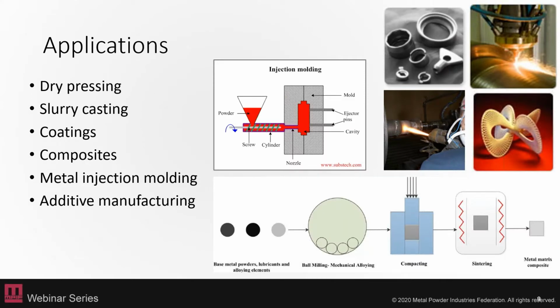And just on a high level, the powder metallurgy field is so broad and includes so many different areas that each of these areas are going to have different considerations for handling and quality. And maybe the area that you're in can learn from another area, or maybe your area is less complicated than another. So different factors are going to be important for different people or in different industries, such as dry pressing versus slurry casting versus coatings and composite materials versus metal injection molding versus additive manufacturing. Just for example, if you're making a metal matrix composite, you're mixing together base metal powders, lubricants, and alloying elements. So there you need to be a lot more careful with the mixing versus maybe your metal injection molding, which is a really narrow, fine size distribution. So your mixing isn't as important, but your handling is more important there because your fine powders are going to be more of a safety consideration. So all of these pieces need to be taken into account, and you need to be aware of those processes throughout your entire workflow.